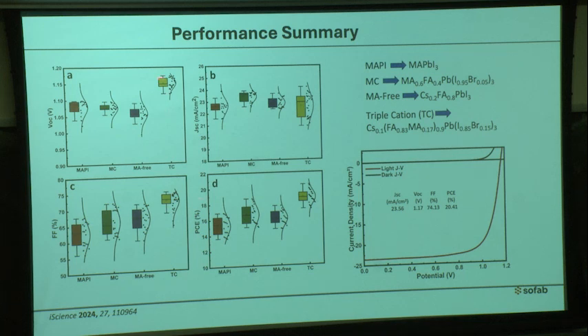If you look here, the power conversion efficiency for triple cation based perovskite is the highest compared to others. Triple cation contains more than one cation - 1 cation, 2 cation, 3 cation - and it also contains 2 halides. Here, if we add cesium, cesium increases the stability towards humidity.